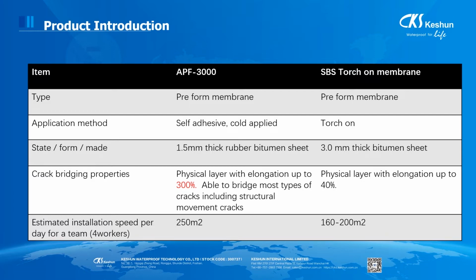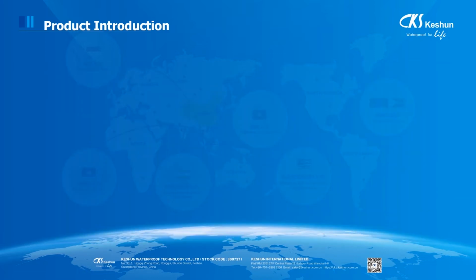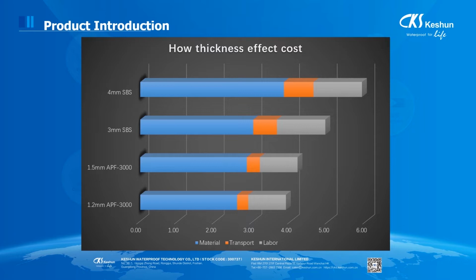And APF-3000 physical layer with elongation up to 300% is able to bridge most types of cracks, including structural movement cracks. And this data is much better than torch membrane. And APF-3000 application is faster than the torch membrane. Then I calculate the material cost, transport cost, and the labor cost in one chart. Apparently, APF-3000 not only cuts down the transport cost, but also cuts down the labor cost.